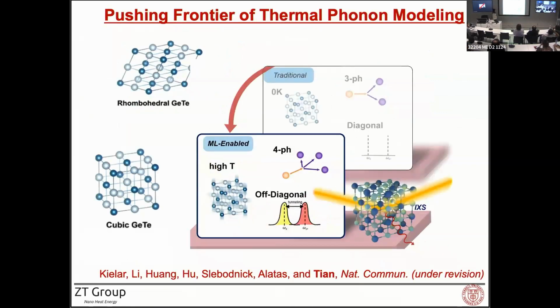So traditionally, we were doing this 0K calculation for three phonon and only considering the diagonal term, meaning that we don't consider any tunneling between branches. But with this machine learning enabled approach, we're able to rigorously include all the three effects. So this work also provides this general blueprint for highly efficient computation of the materials at the high temperature phase.